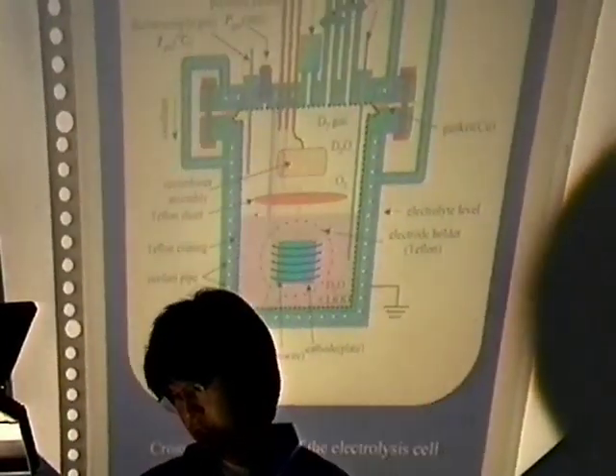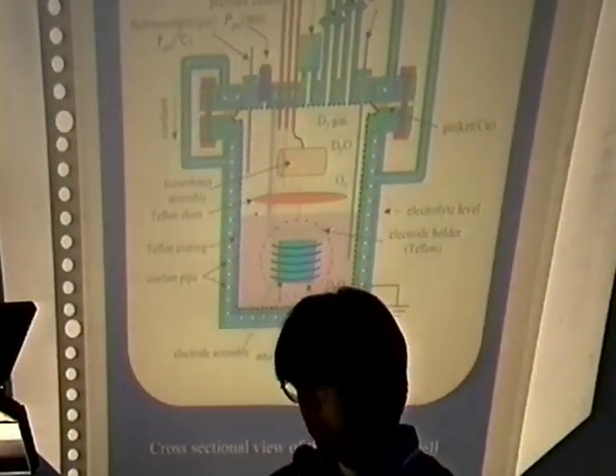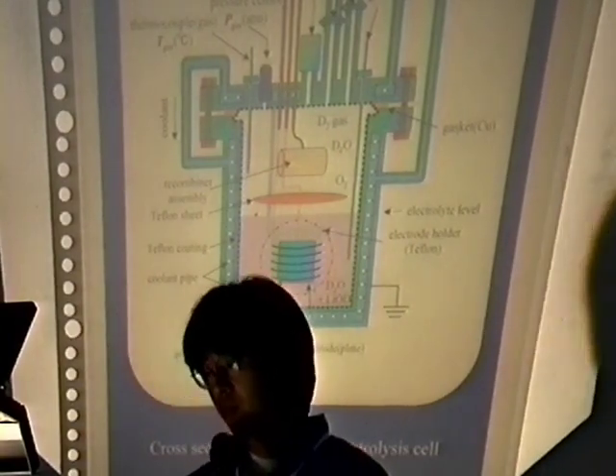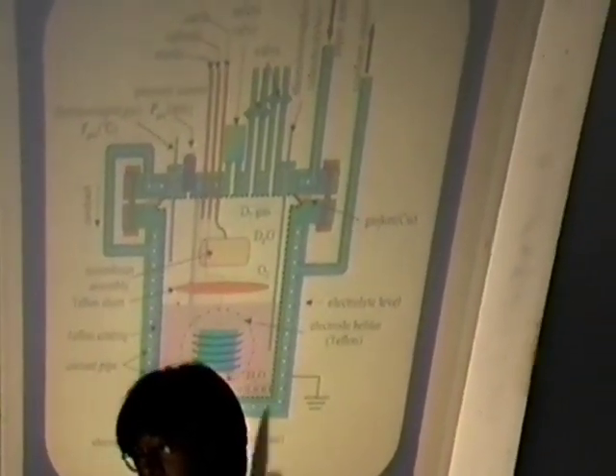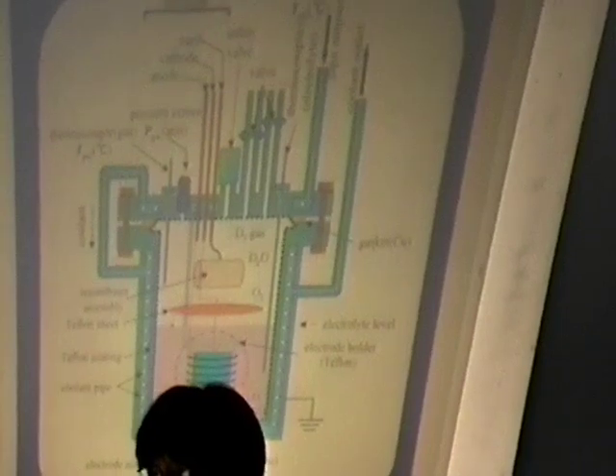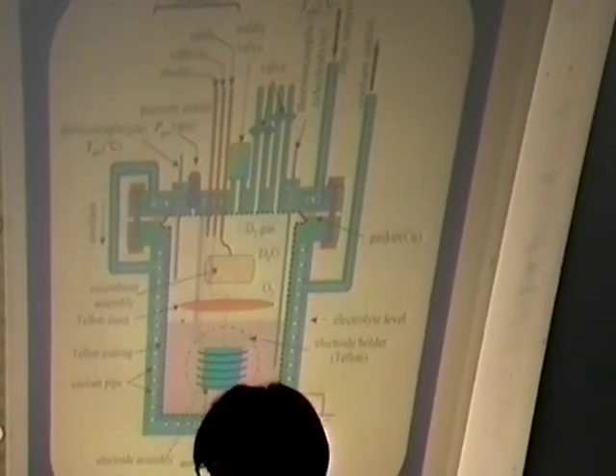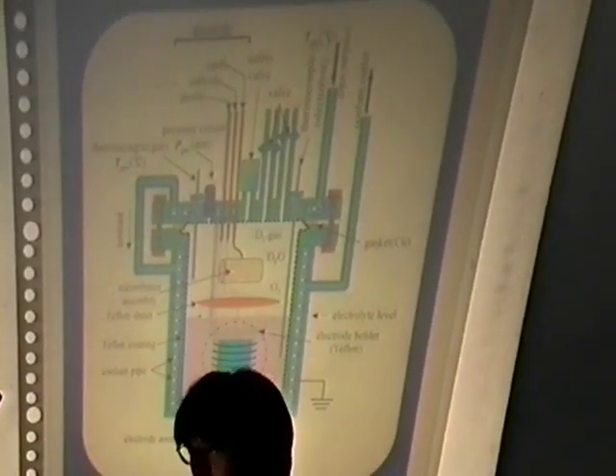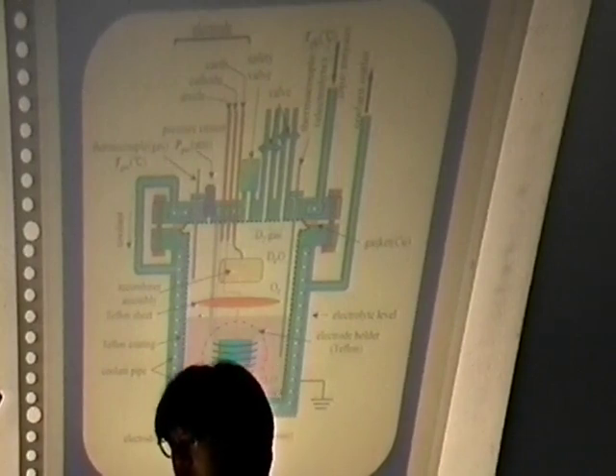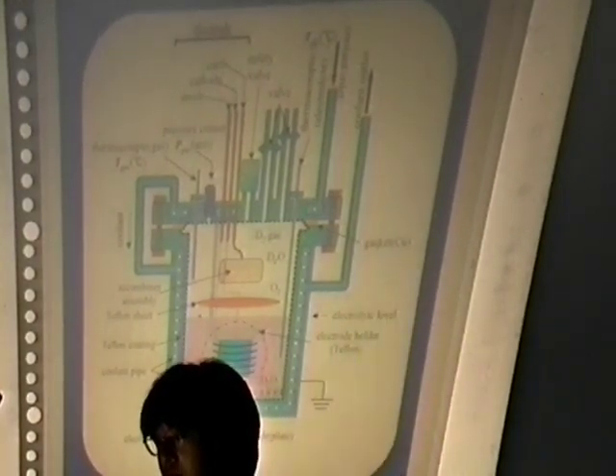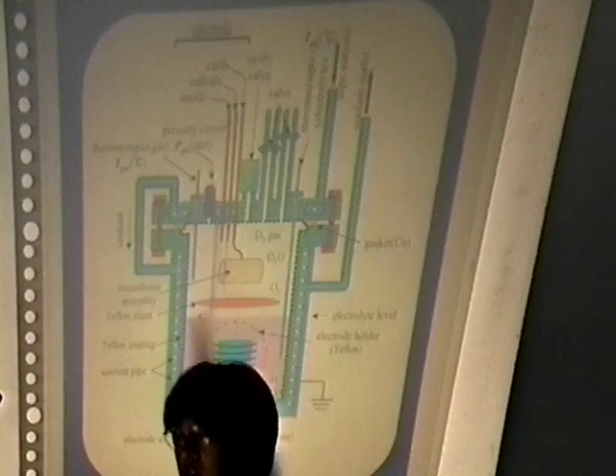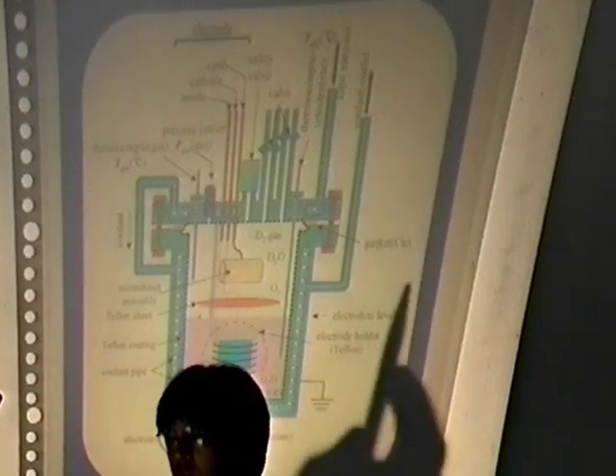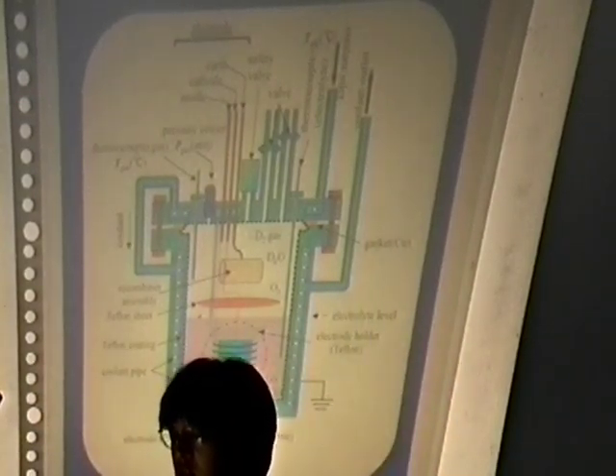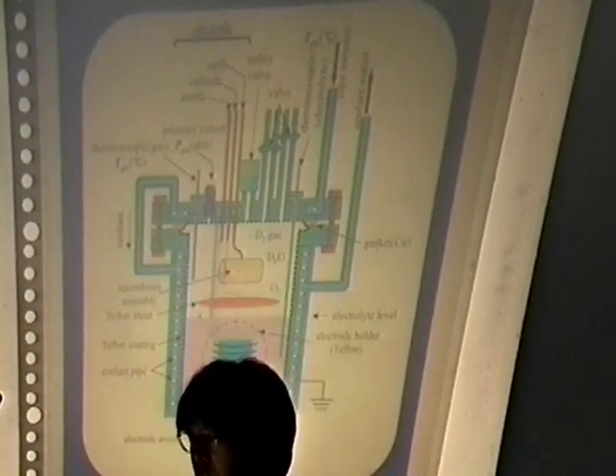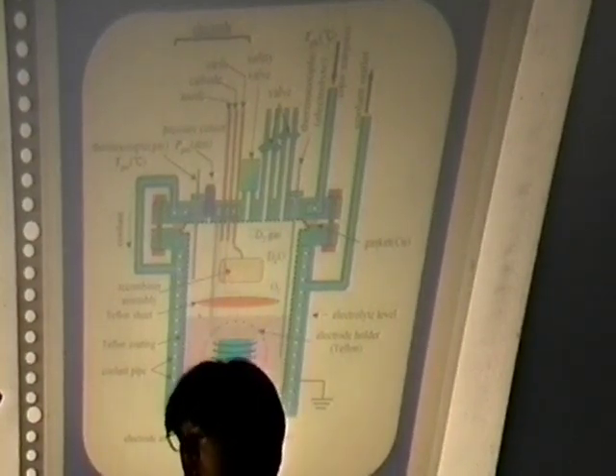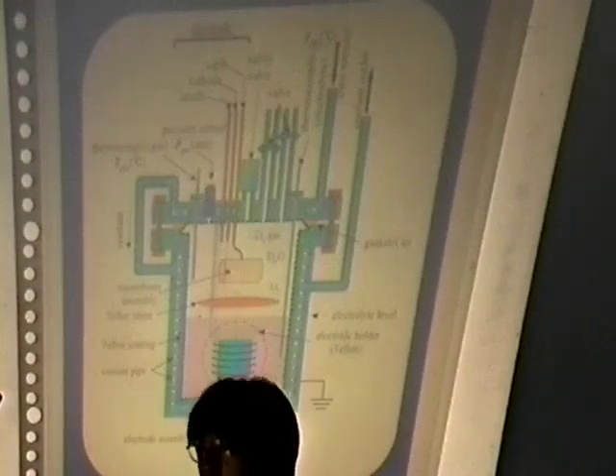This figure shows the cross-sectional view of the electrolysis cell. The coolant pipe was set in the cell wall, and heat recovery efficiency is about 95%. And the cell was sealed with this copper gasket, and internal gas was isolated from the outside gas. And this upper cell gas was analyzed after the electrolysis.